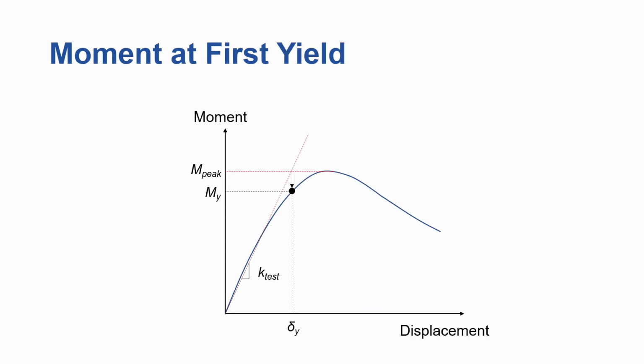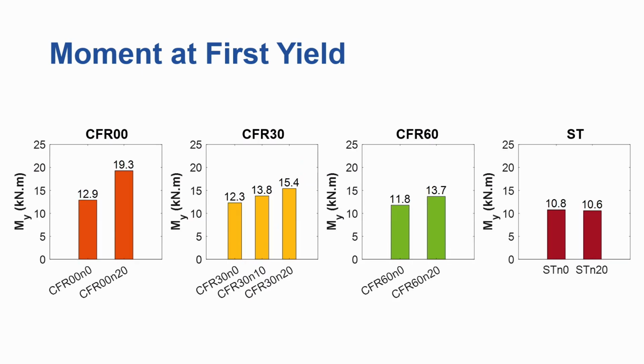Then we looked at the moment at first yield, also from the envelope curves of the moment displacement curves. And this was estimated as the straight line from the second stiffness coinciding with the horizontal line at the peak moment, and just plotting an arrow down to get the estimated moment at first yield. And then these are the results for different specimens. One thing we noticed for the concrete filled specimens is that as the axial load level increased, the moment at first yield increased across all concrete filled specimens, but as the rubber content in the concrete infill increased, the moment at first yield reduced slightly.